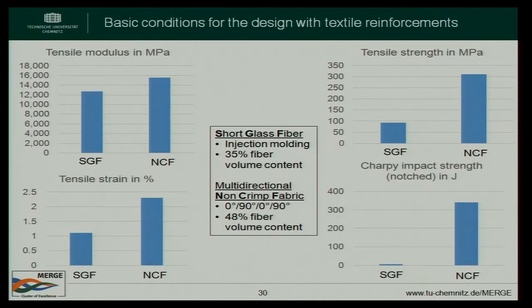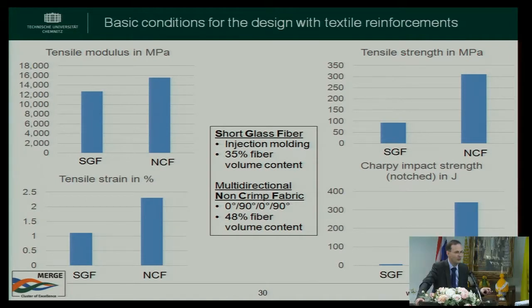So, for example, you see here a nice piece of research we made. We compared polypropylene injection molded parts with glass fibers. You see here short glass fiber, for which we made the abbreviation SGF, and endless fibers, where we had a multi-directional non-crimp fabric, NCF. Of course, with short glass fiber injection molding, you more or less reach only a fiber volume content of 35%. More is more or less not possible with the technology of injection molding and compounding. With a textile reinforcement, you integrate some non-crimp fabric directly into the mold with 4 fiber layers, 0 and 90 degrees mixed. We reach, of course, a higher fiber volume content of 48%.